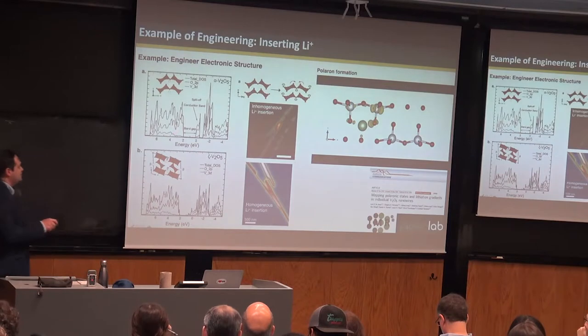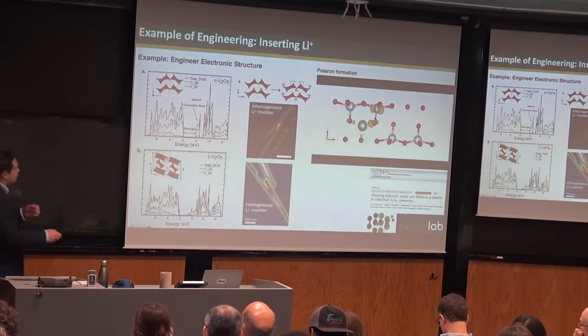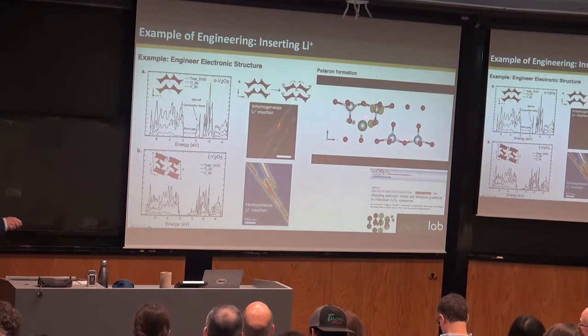This results in a case where if you try and put lithium into this, you're going to get a strong heavy polaron which is going to localize your electric charge. So if you want to move that ion, you have to adjust these bond lengths, and so you get sluggish kinetics, and this results in inhomogeneous lithium insertion.